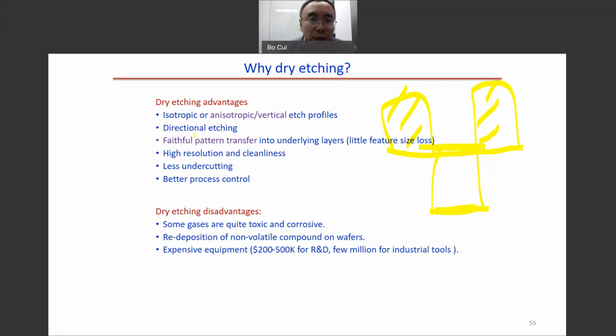On the contrary, if we do the isotropic etching, it will become something like this. So you see the feature, the opening becomes much bigger than the opening on the mask. This way, wet etching is not good for high resolution, but dry etching is good for high resolution. And we see there is no undercutting, and better process control.